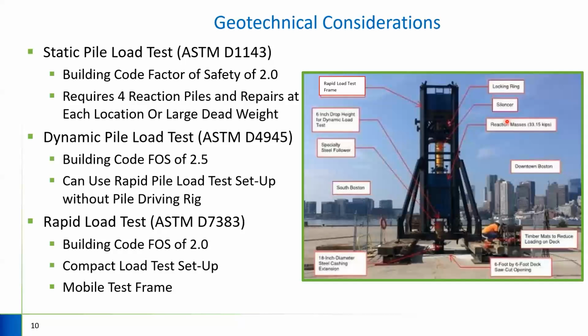Additionally, for the rapid load tests themselves, we were able to use a building code factor of safety of 2, since this was a direct measure of the force imparted upon the pile, and it's a very compact load test setup and mobile test frame. And so for schedule concerns, we were actually able to conduct one series of dynamic and rapid load tests per pile per day. And so we were able to do the actual load testing within 3 weeks.